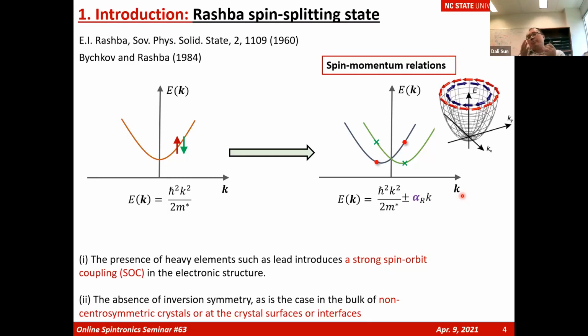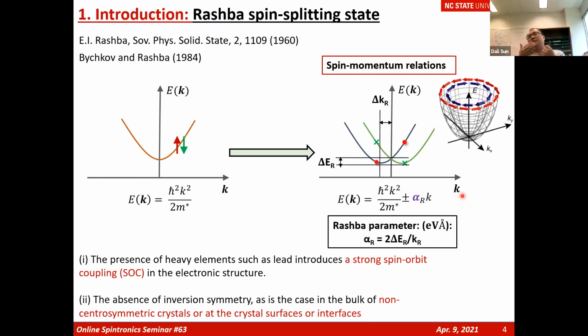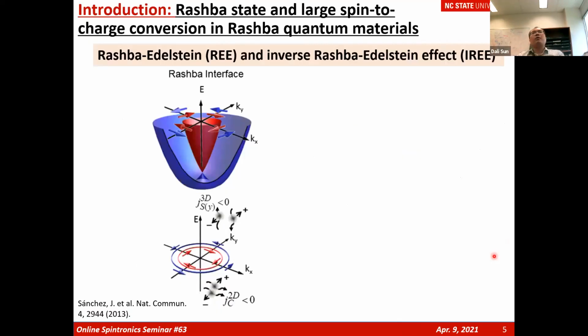Here we're mainly focusing on the first term, the Rashba effect, defined by the Rashba parameter, the energy shift divided by the k value. Usually people use this Rashba coefficient, the Rashba parameter, in units of eV·Å, to determine the Rashba effect in a crystal or semiconductor. So why is the Rashba effect so interesting in quantum materials?